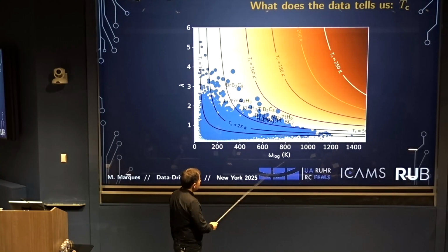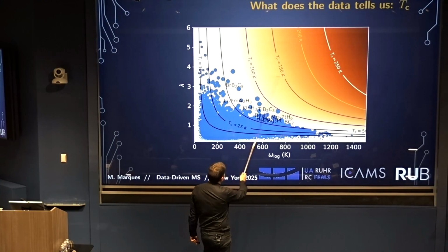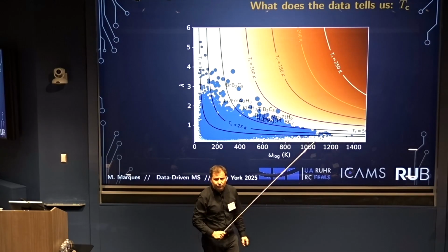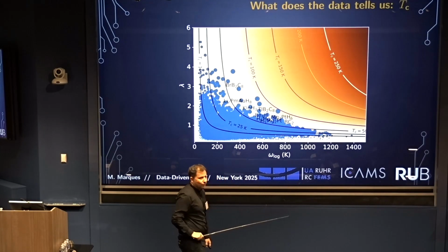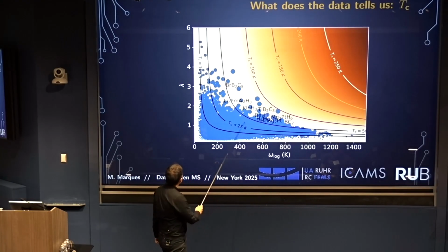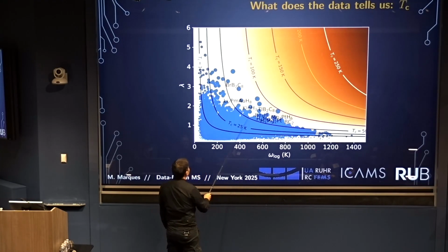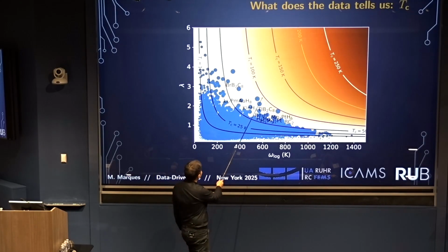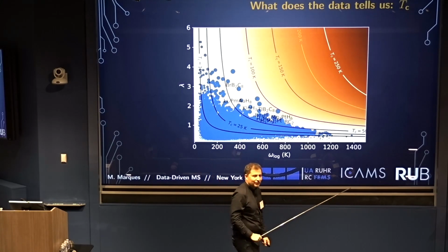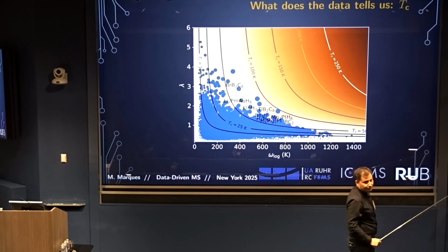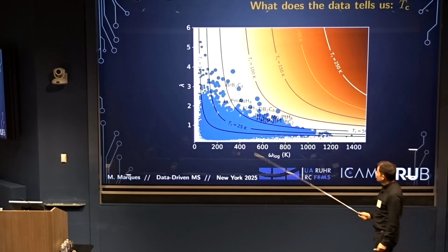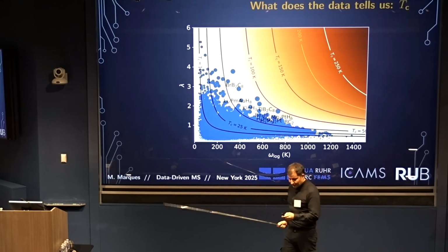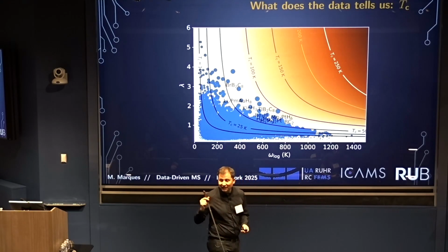But anyway, distribution of TC. This is omega log. This is lambda. The color is just McMillan's formula for you to have an idea of how TC changes. And this graph is amazing, right? Look, 50 Kelvin here, so many things. Yeah, even 100 Kelvin. That's wonderful. There's no problem in finding conventional superconductors with TC at 100 Kelvin, even more. You see it here. There is no problem. So what is the problem? Who can tell me what the problem is?